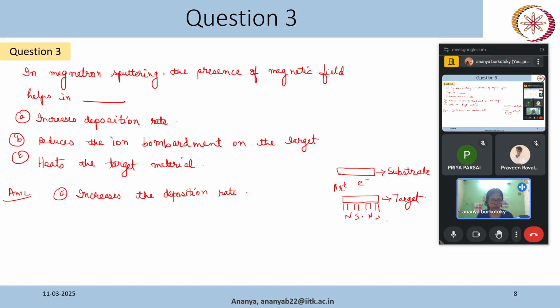The reason is, these are magnetic fields because of these magnets here. And we discussed earlier that electrons and ions will be affected by the magnetic fields or electromagnetic waves, right? So we already know this, like if there is a current carrying conductor, there will be magnetic field around, and magnetic field actually changes the current and all these things, right? So because of these magnets, your plasma or your ions will be trapped near this target. So the sputtering ions will actually hit the target again and again, and your deposition rate will be faster because it's not one bombardment, it's multiple bombardment due to the presence of this magnet with the same argon ions. Okay, so that actually increases the deposition rate.